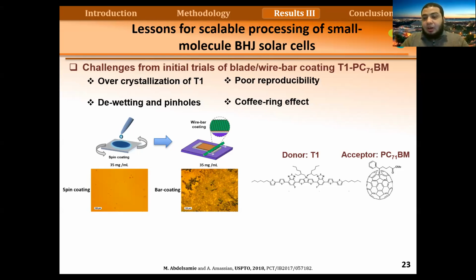So in order to overcome this, we investigated the spin coating and bar coating in situ, and we found the problem comes from the wire bar coating itself. It was inducing larger scale phase separation, and also was inducing over-crystallization because the T1 material was crystallizing in solution at room temperature. If we do the wire bar coating at room temperature, and if we increase the temperature, we also get the same problem with very large domains of the T1 material.